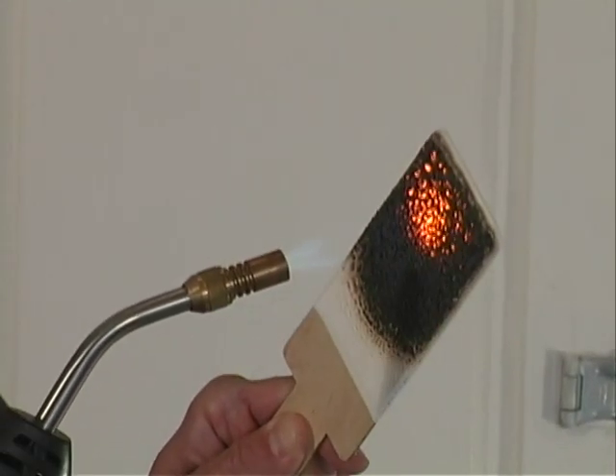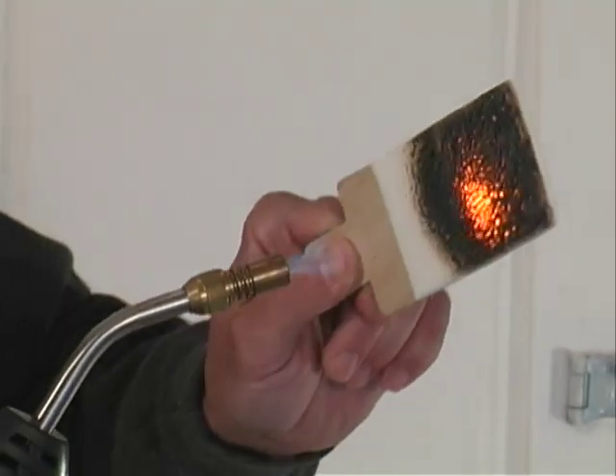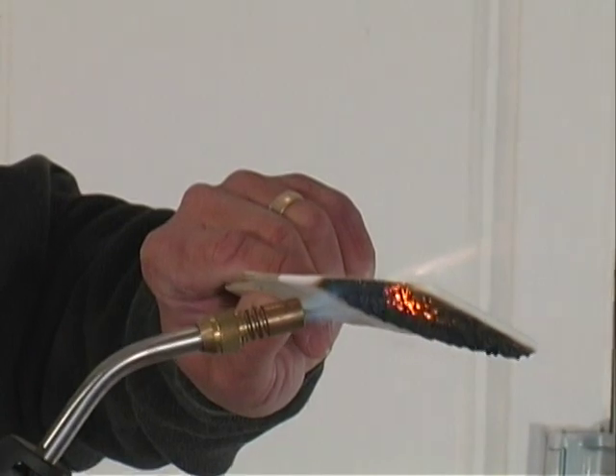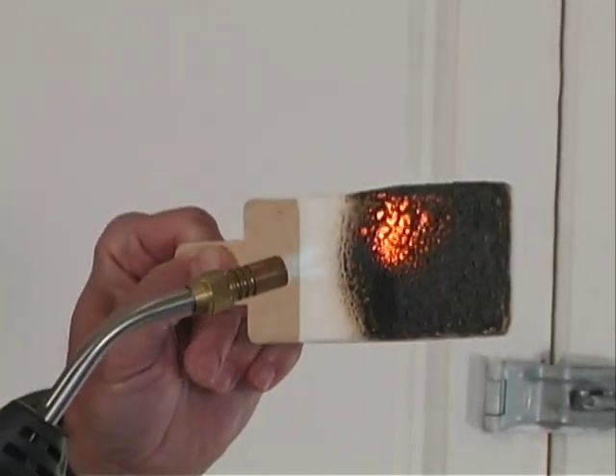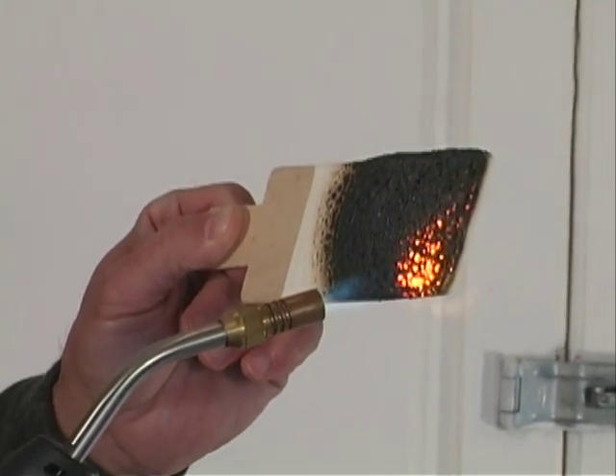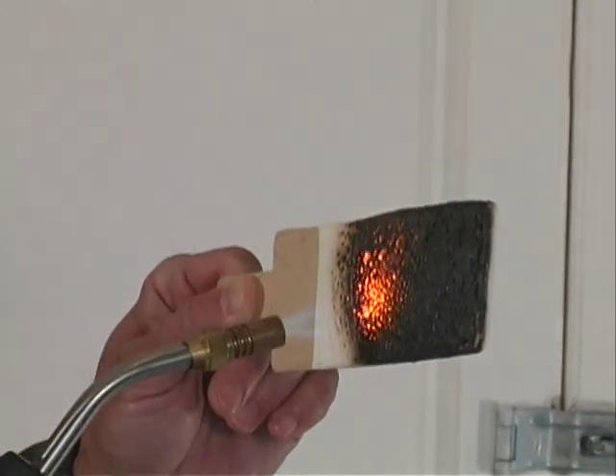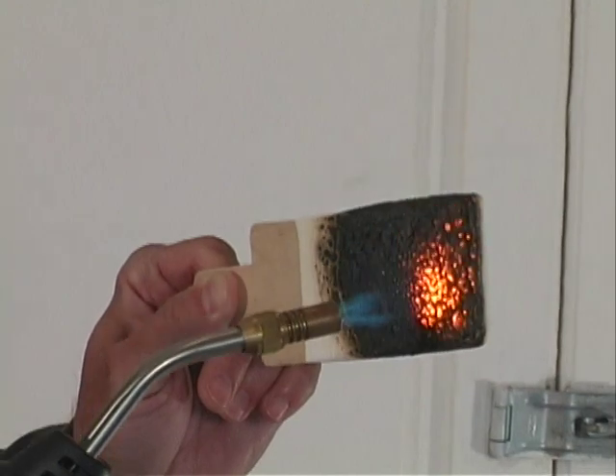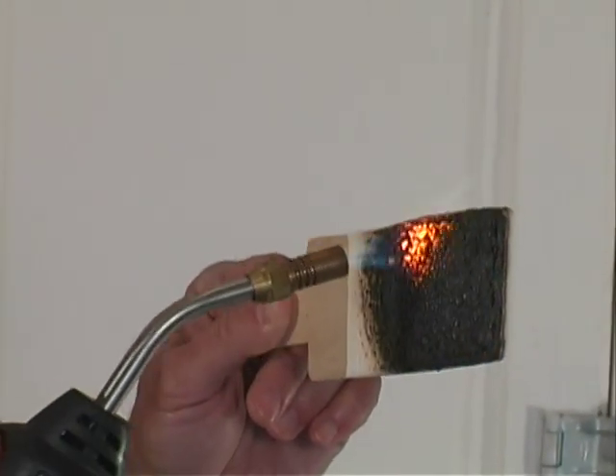Keep in mind, this paddle is an extremely thin wood paddle, only about 3/32nds of an inch thick. Most intumescence can't travel around an edge, but notice how the Contego product swells up to protect even sharp edges. As demonstrated in the photographic support and tests on the CD-ROM, you'll see that Contego responds like no other intumescent you've ever seen. Notice how the longer we keep the fire on the stick, the thicker the char layer gets. The product responds comparatively to the amount of temperature and the duration of the fire.